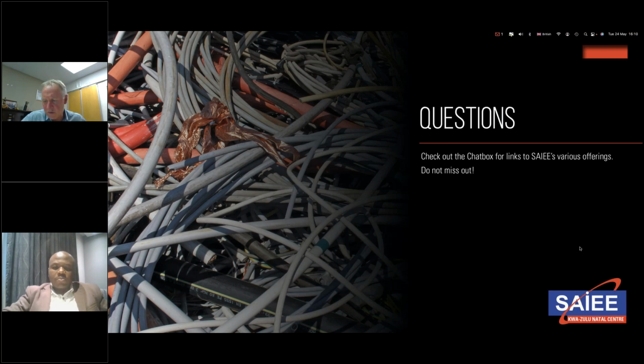The issue with these kinds of cables that one would use aluminium or potentially CCA in would be fixed installation cables, and for those cables the defining criteria would be the insulation: that as you bend the cable you don't want the insulation to be damaged from the pressure exerted by the layers above, whether it's copper tapes or copper wire screening or armoring that exerts pressure on the bottom layers.